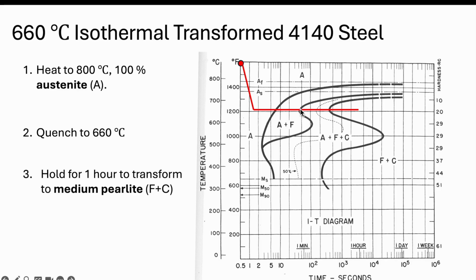Here you'll notice that we're at this kind of nose of this C, the part that juts out the most. So this reaction starts the quickest of the perlites, right? We're right in the middle. And so this starts after about a minute and finishes well before an hour if this is the case. So we don't actually need to go more than an hour in this case to get this pearlite.